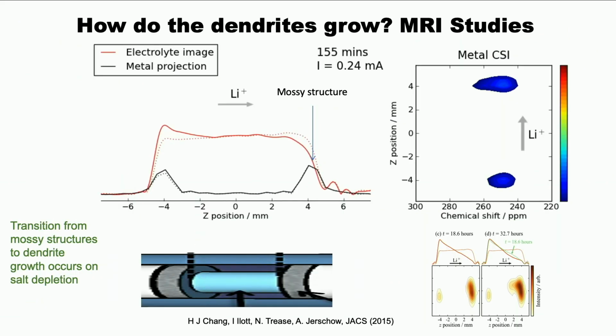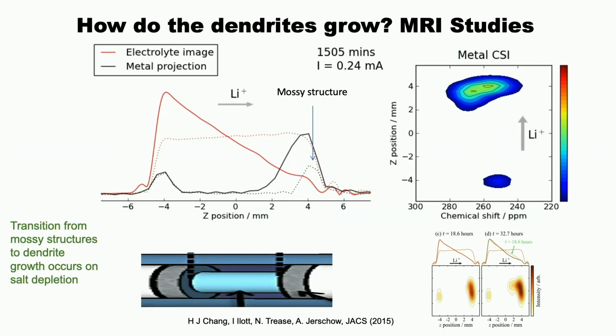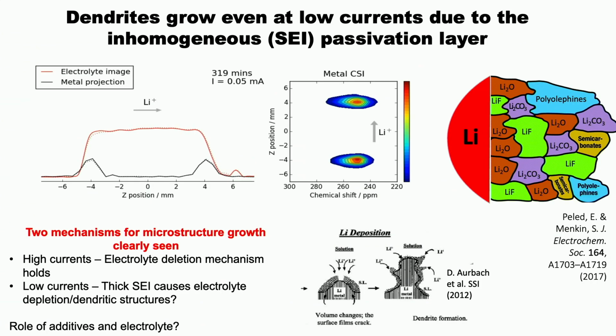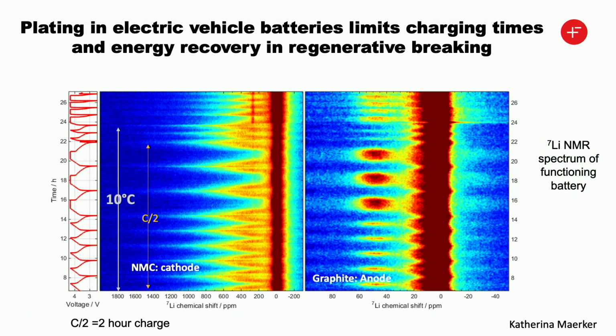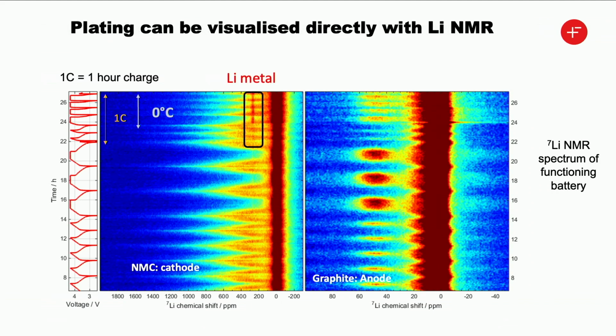So we can do beautiful experiments. We can do magnetic resonance imaging experiments, and we can track them as they're forming, and we can relate that to the SEI formation. That's all nice from an experimental perspective, but it doesn't really help us in terms of fast charging. This is now more recent experiments where we're looking at the full cells. We've got our NMC material, we've got the graphite, and we're looking at charging, and we're charging at increasingly low temperatures, and you can see that at low temperatures you're forming lithium plating. And this lithium plating issue is why in regenerative braking you can't utilize all of the kinetic energy to charge your battery, because of this worry about lithium plating.